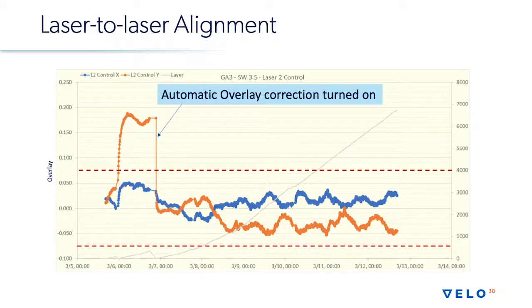And what we're doing here, this is a plot of a build where, again, we don't have our thermal management system on. So when you first start the build, it'll heat up, your alignment will shift, and that's what you see going on here. We turn on our automatic overlay correction, which basically is taking these measurements, in this case I think it's every layer. It's kind of overkill, but it's a proof of concept feasibility study. So you turn this on, and the system starts to actively control its laser alignment in real time to make sure that on every layer throughout the entire build, your alignment is correct.